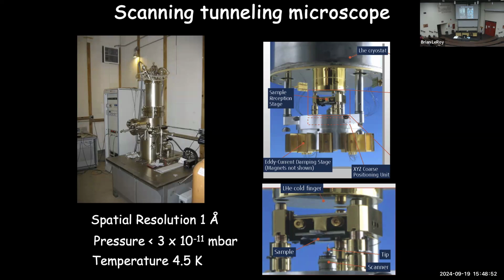to the surface. So we need this ultra-high vacuum to keep it clean, and we need low temperature to enable us to have good stability of the system. By cooling down the system, everything basically is frozen, becomes solid, and that allows us to have our tip-sample separation be very stable. The other thing it allows us to do is this sets the energy resolution of our experiment.